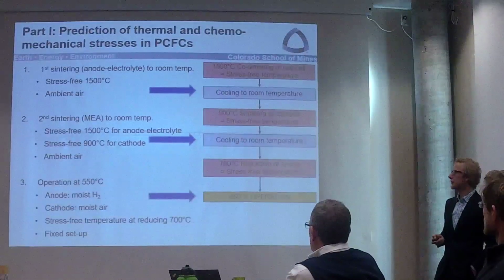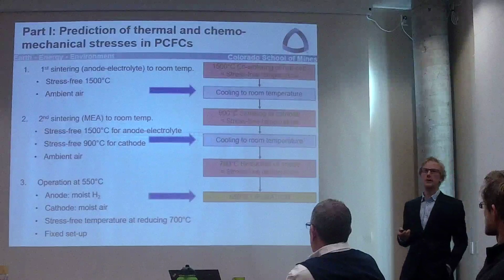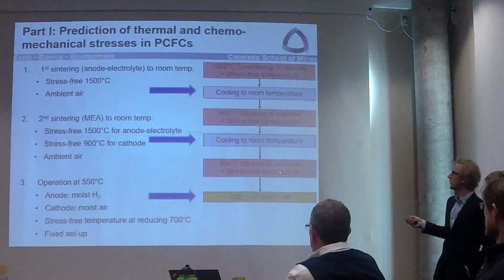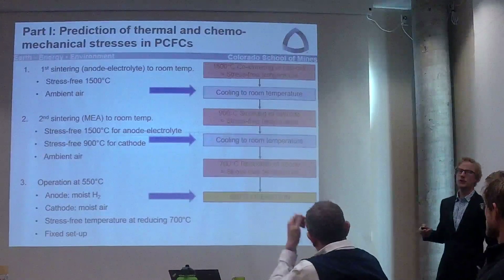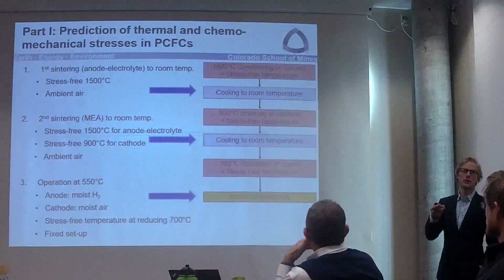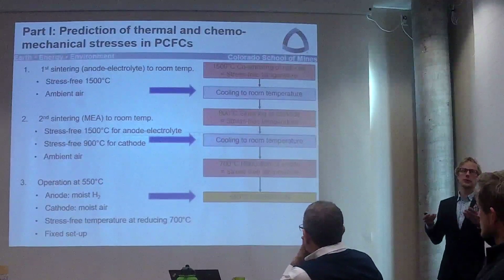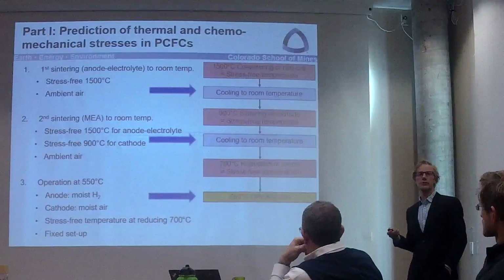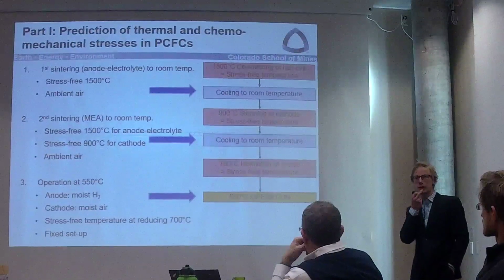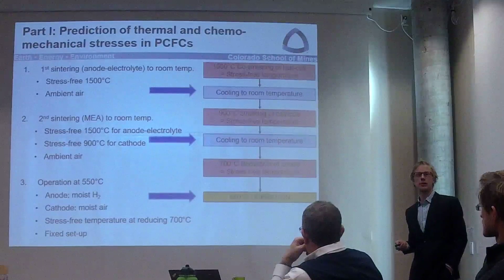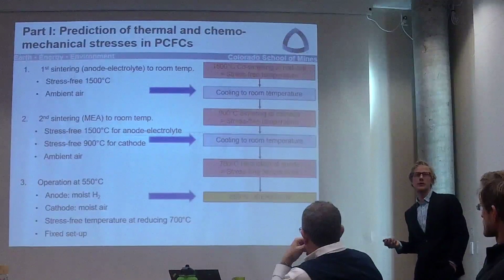And then the third critical step is once you start operating the cell. So here we assume that at 700 C, when the anode is reducing from nickel oxide to nickel, the ductility of the nickel will release a residual stress, and so you cool down to 550 C, and that's only at 150 degrees C delta T. So here the thermal stress won't be that important. And mostly the chemical stress due to the how do those thermal and chemical stresses come?